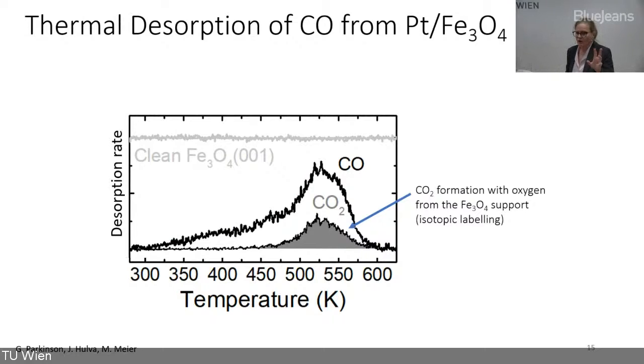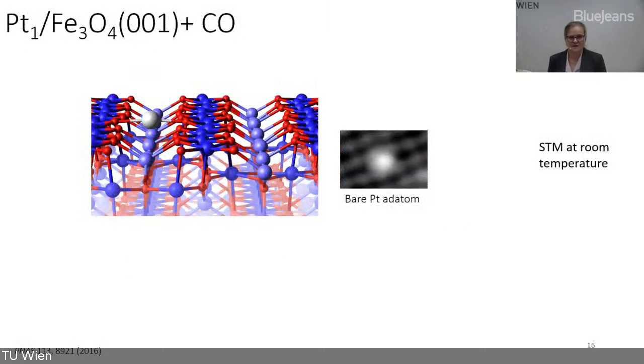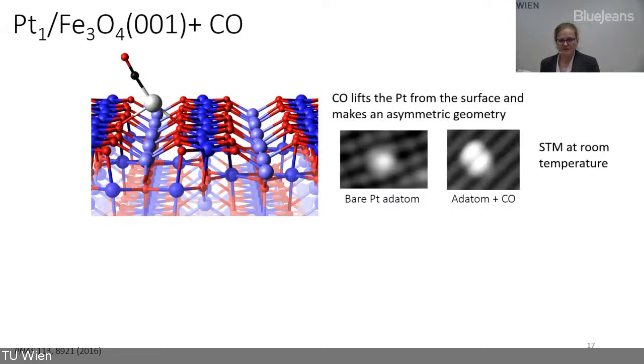We can monitor the reactivity of these single atoms, but with STM we can also look at what happens. This is an STM image - the gray one is taken at room temperature. On the left-hand side, you can see the calculated configuration with density functional theory. What happens is when you put the CO molecule on top of it, the CO interacts.